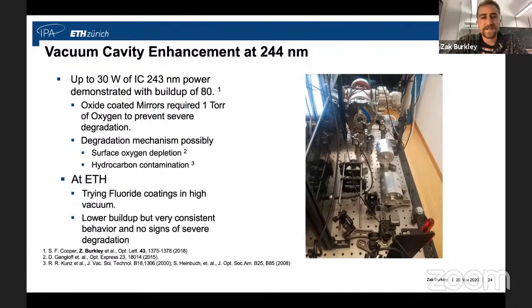Yeah, it's a great question. And so I have some experience with this through my time in Colorado and here at ETH. Originally, these enhancement cavities that we built, we used a few silicon mirrors with a silicon oxide coating. And we saw with these oxide coated mirrors, they required 1 torr of oxygen to prevent severe degradation. If you went below this 1 torr of oxygen, there would be contamination on the mirrors in vacuum. You could remove it and scrub it off and put them back in.